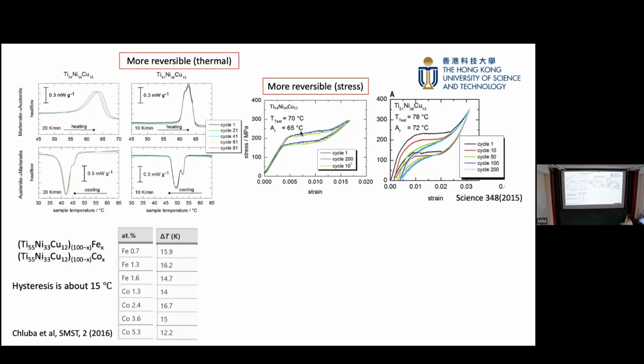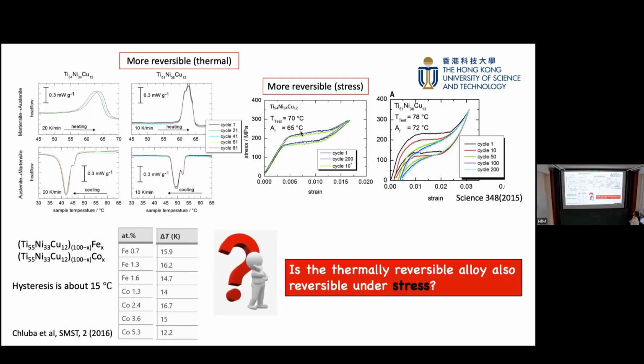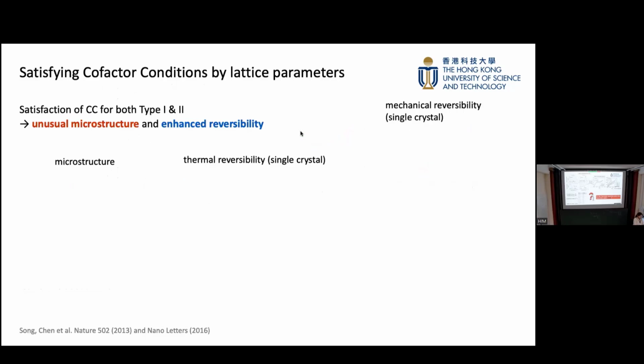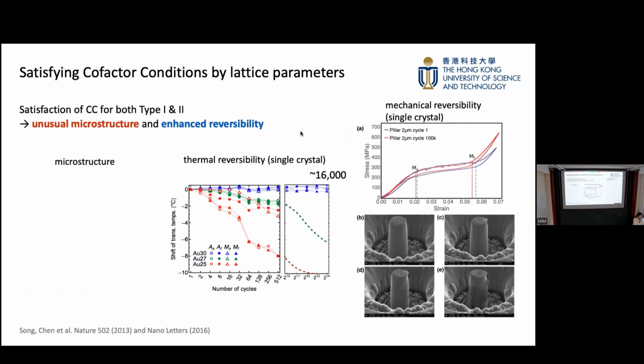And then my collaborator, Eka Kwan, did very helpful chemical doping with some other element, a very delicate kind of doping. They find the hysteresis is more or less 15. The lambda 2 is quite close to 1, but each of the materials has different mechanical reversibility. So now I really want to ask a question: is a thermally reversible material still reversible if we put it under stress?